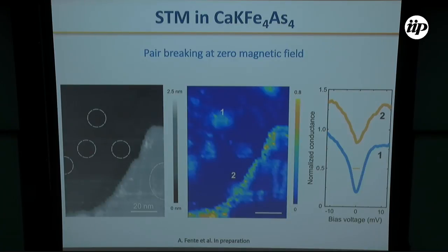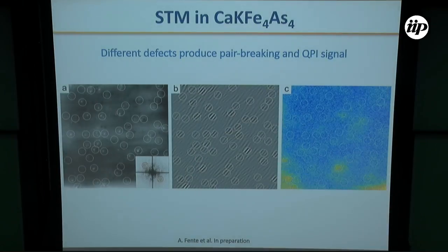We found that close to steps or small holes, close to defects, we have an increase in the density of states at zero bias. We have pair breaking. So this is consistent with the fact that most likely we have an S plus minus superconductor. So these defects most likely are producing scattering between parts of the Fermi surface where the gap changes sign. I don't have time to go into details, but we have also observed that the defects producing the QPI signal are different from the defects producing the pair breaking.